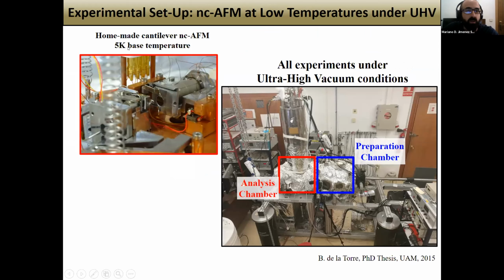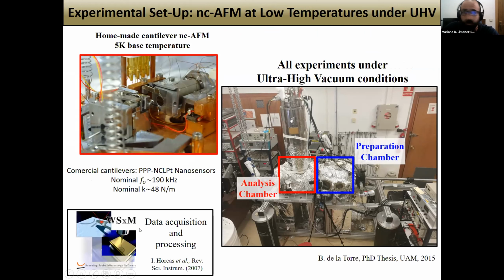And what have we employed to do this work? Well, all the experiments have been performed under ultra-high vacuum conditions in this system, which has an analysis chamber equipped with a homemade cantilever non-contact AFM, which is operated at 5 Kelvin. All the measurements have been performed at low temperature. This AFM is operated with commercial cantilevers from the Nanosensors company, and the data acquisition and processing have been performed by means of the WSxM software.